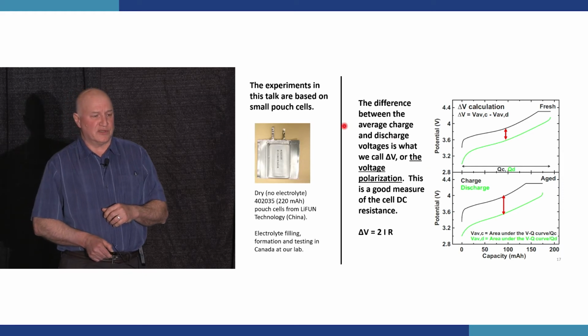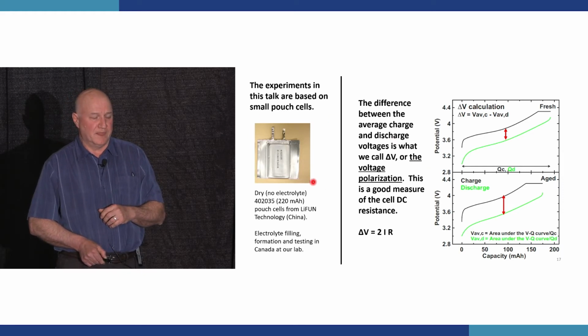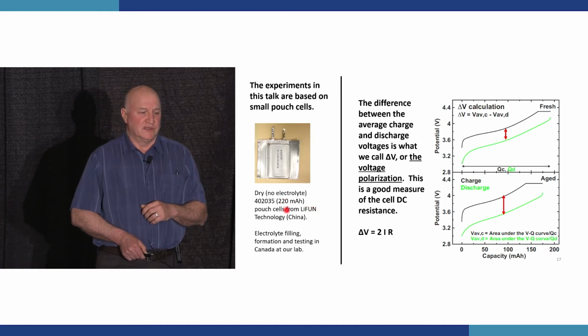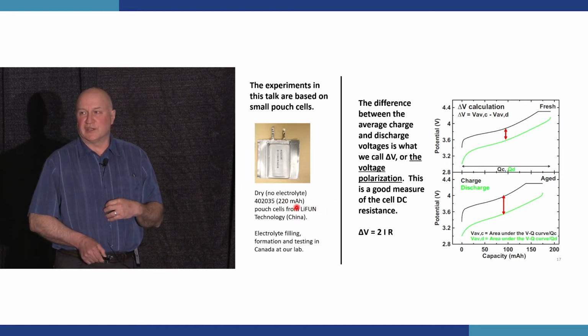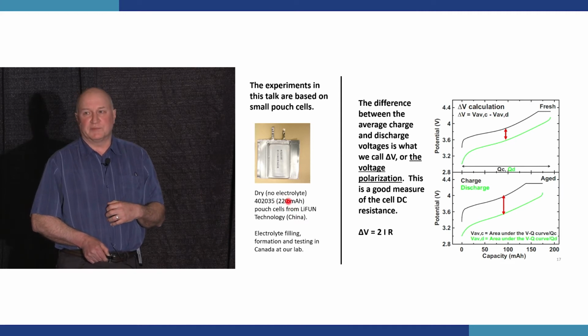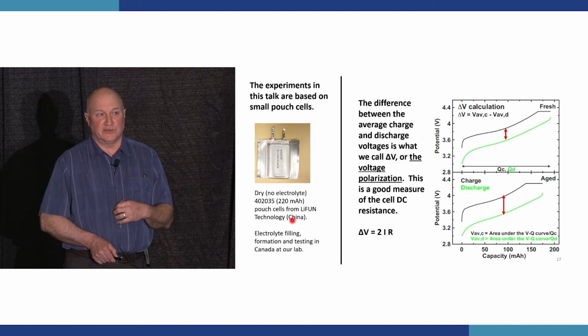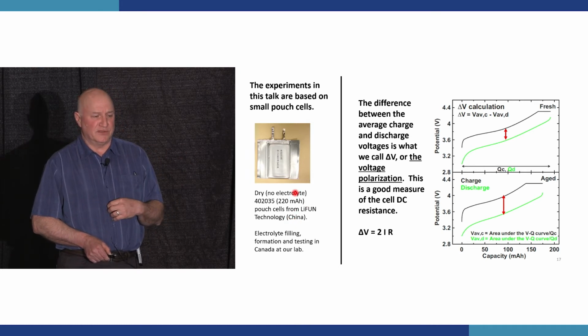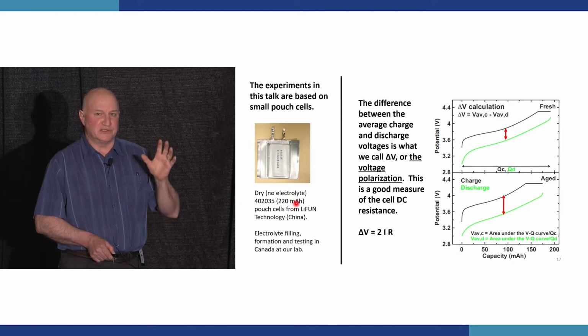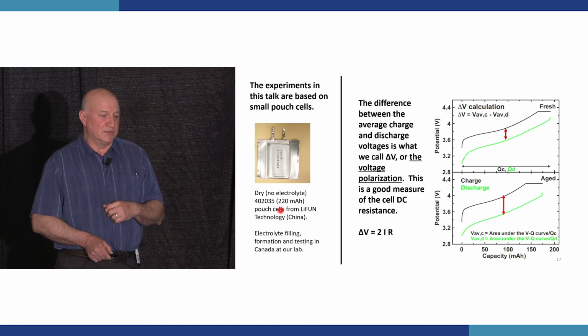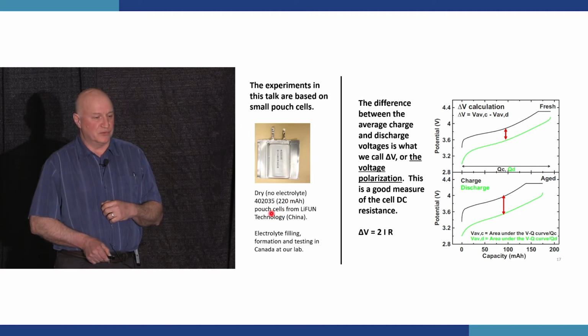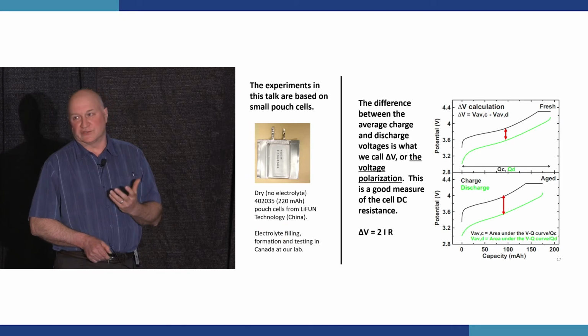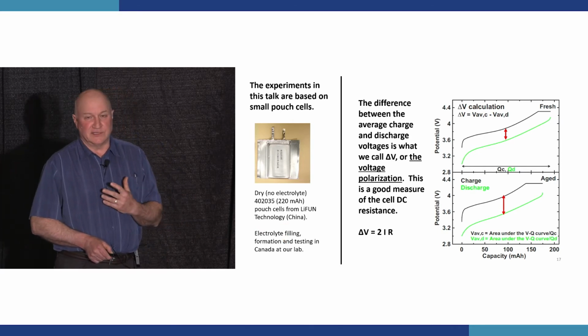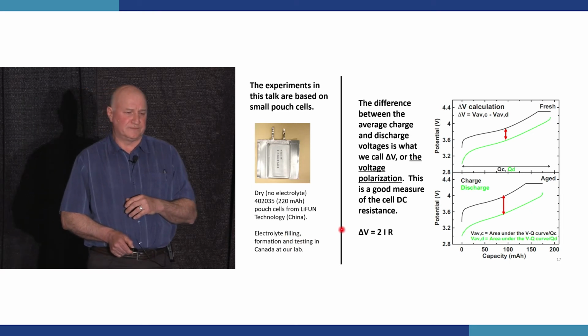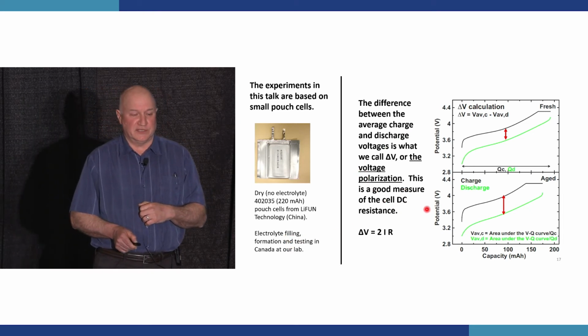So the experiments in this talk are based on these small pouch cells shown here. They're about 220 milliamp hours. We get them made by a company in China called LiFUN Technology. We specify what the electrode materials should be and the loadings and the cell design. And then LiFUN has a manufacturing line that makes these for us in 1,000 lots, basically. They're all machine made and all exactly the same. But they come to us dry without electrolyte. So we fill them with electrolyte, and that gives us control over the electrolyte additives and the electrolyte type, which influences lifetime a lot.